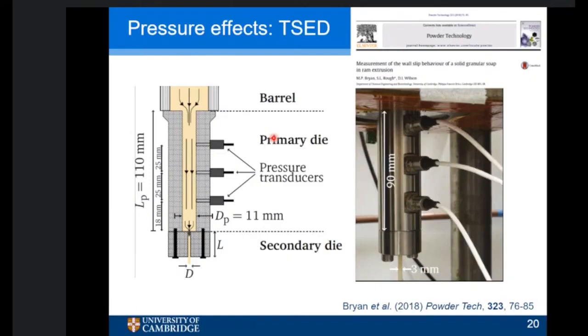That's a good question, Sabi, and I don't know the ultimate answer. One of the reasons is it's a couple of die diameters. So just on a geometrical relationship, let us have it a couple of die diameters apart. Okay, so if there's anything related to length scales in that flow, we would do that. The other point is, of course, how close can you get them to be in terms of machining the things? Because these pressure transducers they're not that small. And so you do have a confinement issue. This is one of the reasons why in the latest version they are located at different positions around the cylinder, so they don't interfere with each other.